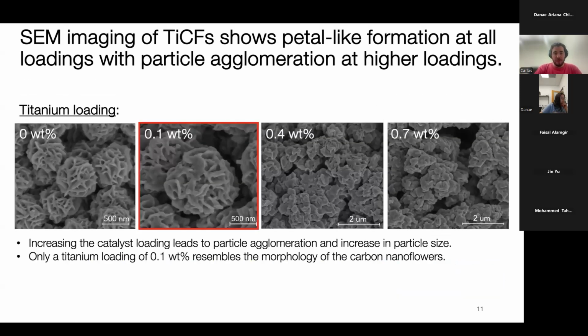So the first thing that we did is, we wanted to make nanoflowers, and what we found is the more titanium loading that we add initially in this synthesis procedure, it affects the way our particles agglomerate. So you can see that most of them have a petal-like structure, even at very high titanium loadings. But once you pass that 0.1 weight percent of titanium, you can see that the particles start to agglomerate. We didn't really want that in order to maintain that nanoflower architecture. So for most of the research I'll be presenting today, I'll be showing you this 0.1 weight percent nanoparticle. And it just happens to also be the best one in terms of performance. So that's why we went with it.